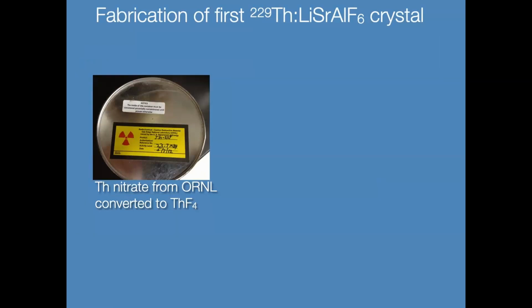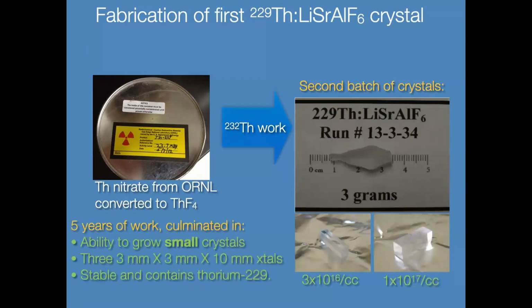So we nonetheless worked on this for a number of years, and then after about 5 years, we were able to get the thorium with a lot of help from Oak Ridge, and then grow crystals that incorporated the thorium into them. The crystal we use is lithium strontium aluminum fluoride. The choice is it's a very high band gap crystal, greater than 10 eV. It also has some of the lowest radiation-induced fluorescence of any material that we surveyed.